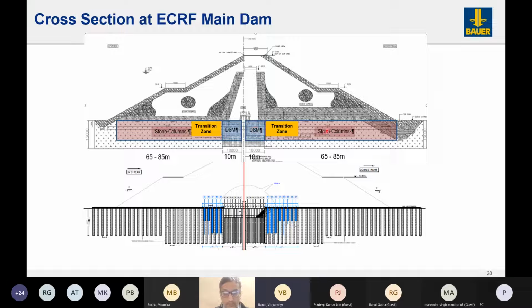Apart from that, when the stone column has been installed here, there is a probability that the change in the strength of the soils is so sudden: the cutoff wall has a high strength, then the DSM has a slightly reduced strength, and stone columns have further slightly reduced strength. But the transition has to be smooth in order to ensure that the strength dispersion along the width of the dam is properly done. We have designed a transition zone of around another 10 meters to ensure that the soil parameters are decreasing gradually towards the width of the dam, because here the height of the dam is quite high and the stresses are also quite high.